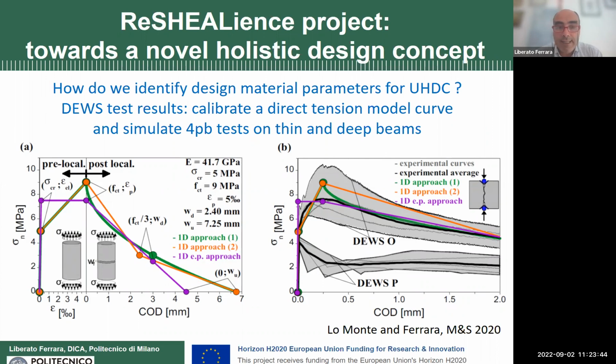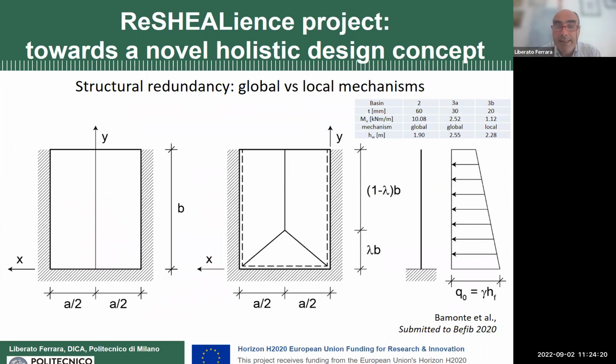These are the results of the identification tests that we made employing different test methodologies. I will not go into the details. There are the papers that are cited here, but you can see the experimental response, which we discretize by the orange curve there. You have a first cracking at about 5 MPa, but after that you have a stable crack propagation going up to 9, and then you have the unstable localization of the crack, but up to very, very high and remarkable crack openings. And this allowed us to implement these constitutive laws into structural design.